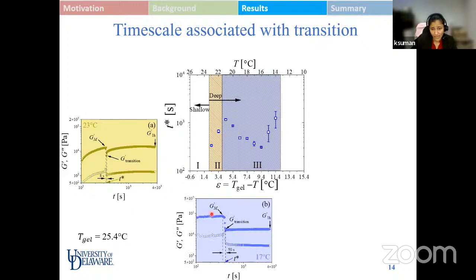As we perform the rheological aging study at a lower temperature of 17 degrees, we see the sudden decrease in the modulus value. However, now there is no continual increase in the modulus value after the transition. It seems to be pretty much saturated after the transition. Over here also the drop is quite sudden, which occurs in a narrow interval of 50 seconds.